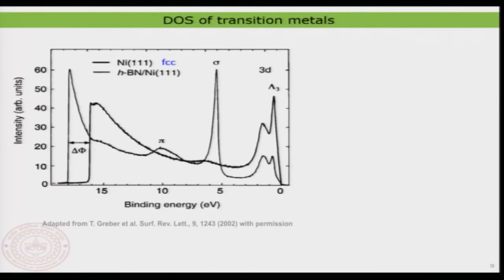So now let us have a look at a slightly different material. What we looked at in the previous class was a noble metal like gold, but here I have a nickel 111 surface, which is known to be quite a reactive surface and also quite an unstable surface. You cannot keep it clean for a long time because it is very reactive. So now when you look at this, here I have two spectra. The spectrum taken on the nickel surface itself is this bold one, which goes like this. This is basically the density of state.